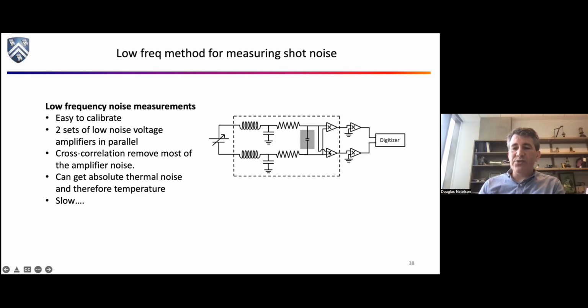So what we do is we take 2 sets of amplifiers in parallel and we correlate them, because the idea here is if there's something really going on in the sample, both amplifiers will see it. But if it's something peculiar to just one amplifier, then when we correlate them, it'll go away, right? And the rest of this stuff out here is just the apparatus you need to quietly apply a DC voltage to your device so that you can drive current through it, right? And you got to be careful about this. You don't want to introduce a bunch of noise with the way you're applying the DC voltage, but that's kind of a lab detail. So you can do these measurements, and some places even do this as an advanced undergrad lab for certain systems.